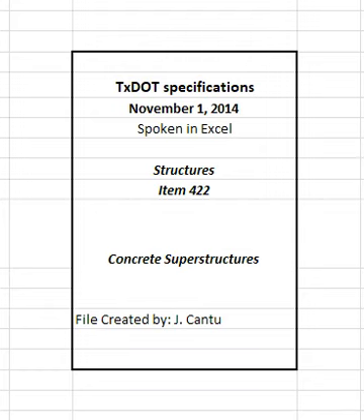Thoroughly clean holes of all loose material, oil, grease, or other bond-breaking substance, and blow them clean with filtered compressed air. Use a wire brush followed by oil-free compressed air to remove all loose material from the holes, repeating as necessary until no more material is removed. Ensure holes are in a surface dry condition when epoxy-type materials are used and in a surface moist condition when cementitious grout is used. Develop and demonstrate for approval a procedure for cleaning and preparing the holes for installation of the dowels and anchor bolts.